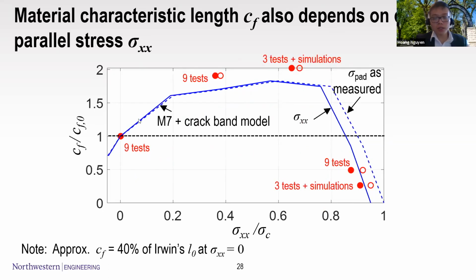The same trend shows when you compare the characteristic length of the material at different sigma xx. If we assume that the characteristic length is 40% of the Irwin's length, then we can calculate the Irwin's length and also apply it to a cohesive simulation.